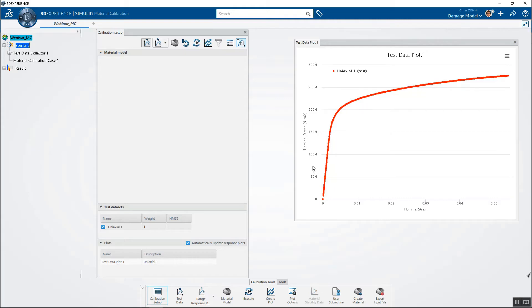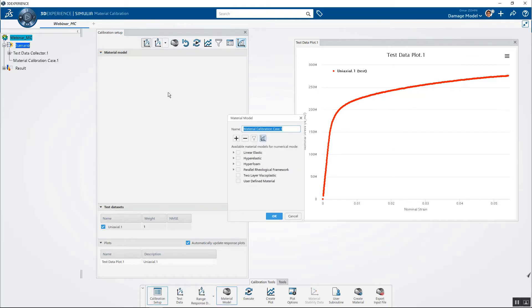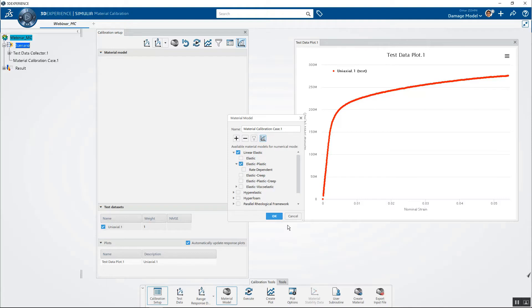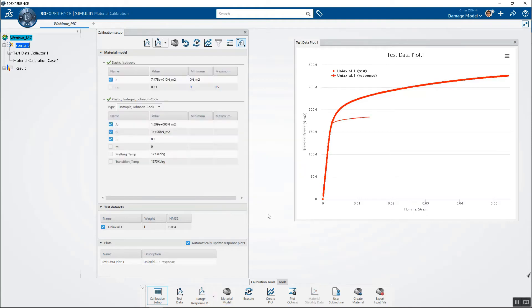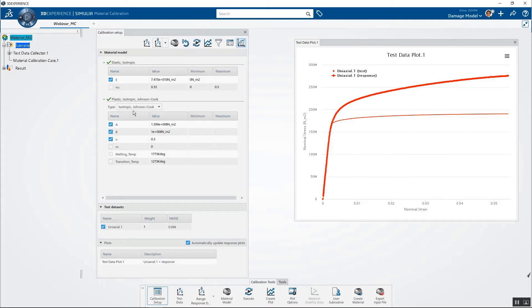Because I don't need to make any changes to the actual curve, I can go ahead and select the appropriate material model. In this case I'm going to use an elastic-plastic material model with no rate-dependent material properties. It's then going to ask which material model I want to use — isotropic Johnson-Cook is probably the most common for this particular model. You can see that based on the initial A, B, and N material constants it's guessing at, the response curve is not yet accurate.